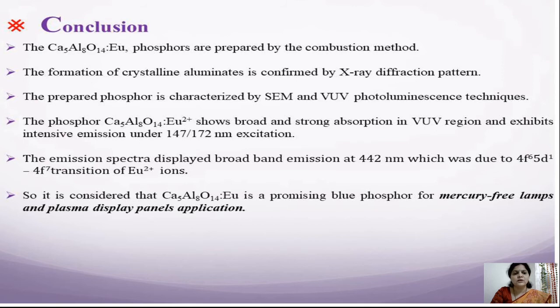The phosphor Ca5Al8O14:Eu2+ shows broad and strong absorption in the VUV region and exhibits intensive emission under 147 and 172 nanometer excitation. The emission spectra display broadband emission at 442 nanometer. So it is considered that the material is a promising blue phosphor for mercury-free lamps and plasma display panels application.